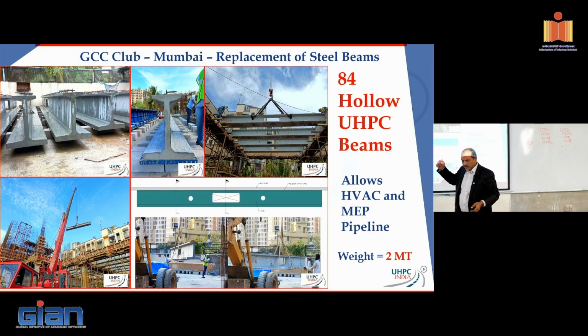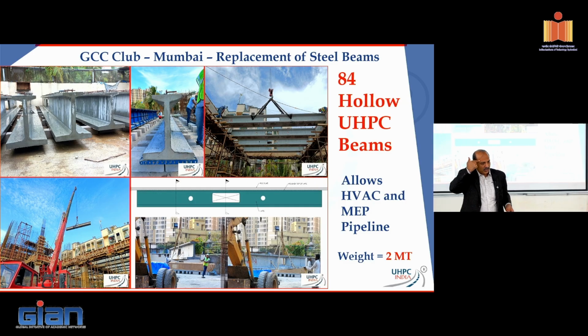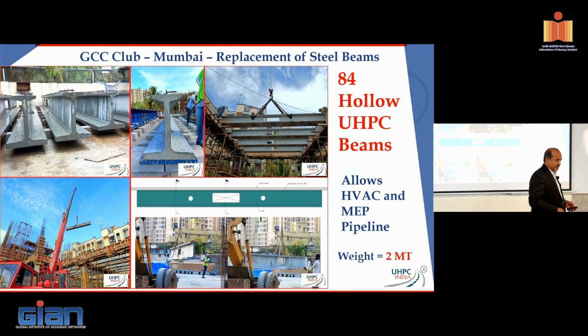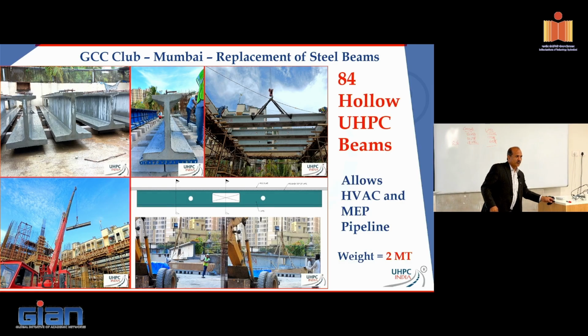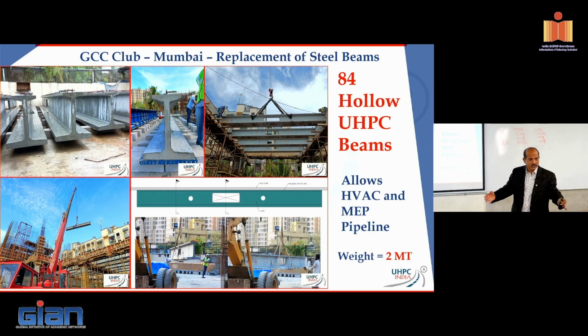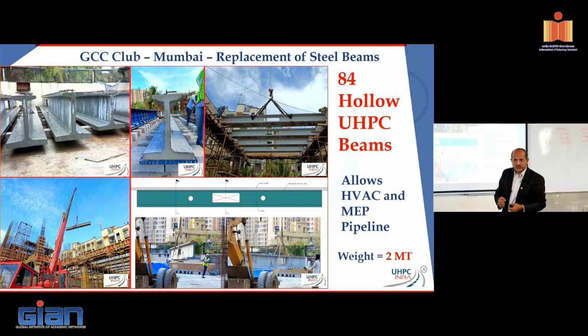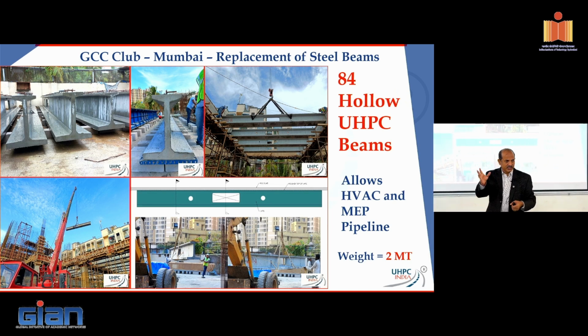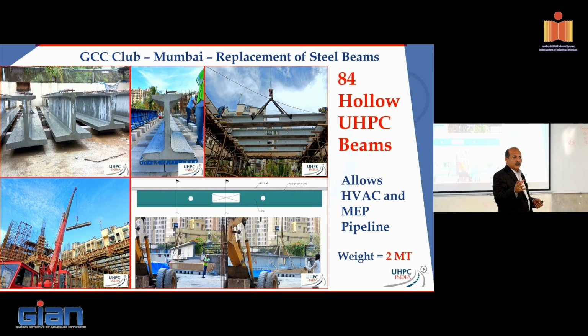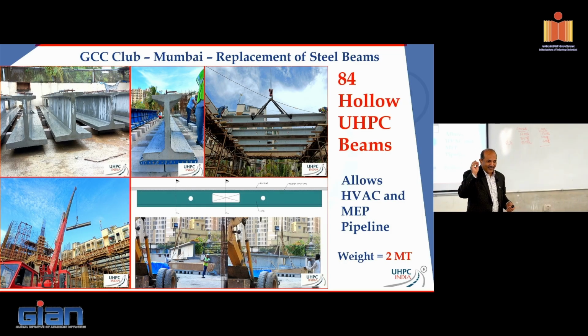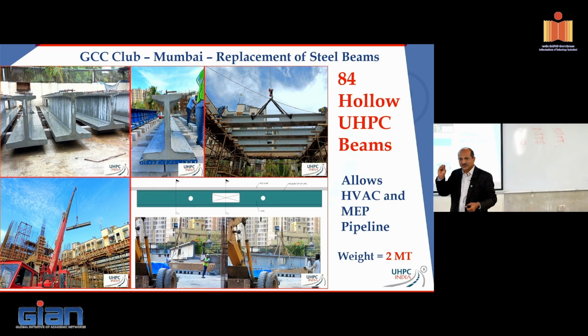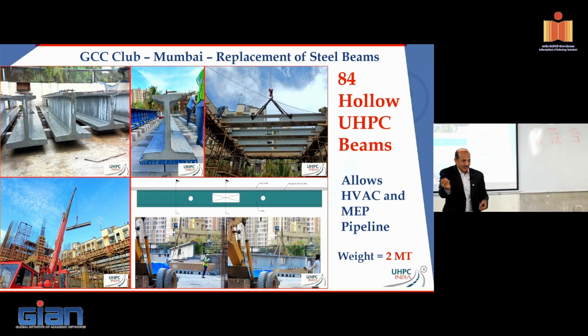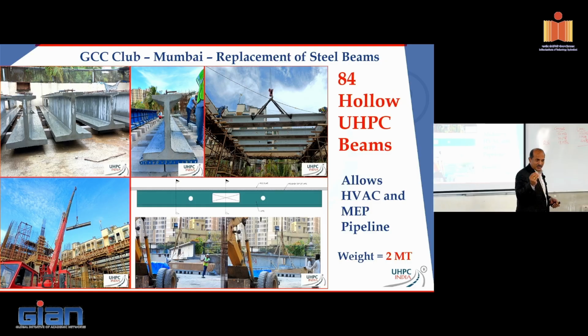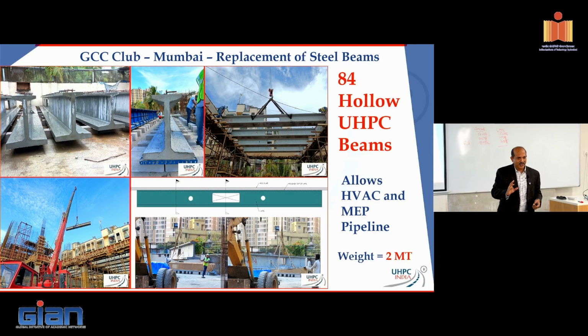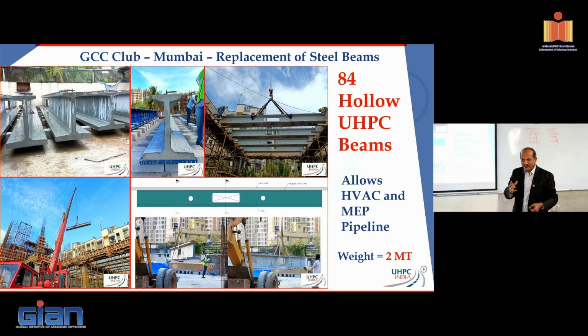There's a question that is not there in my slide, but it comes up time and again during conversations: what do you do about fire? Because generally if you look at UHPC, even with all the steel fibers in it, it's so tight that if you put it in a muffle furnace or under fire conditions, you're going to pulverize it. Now that is something which is not right for building systems, right? For a bridge, that will work in general. Anywhere in the world, bridges are done without addition of anything extra other than steel fibers in UHPC.